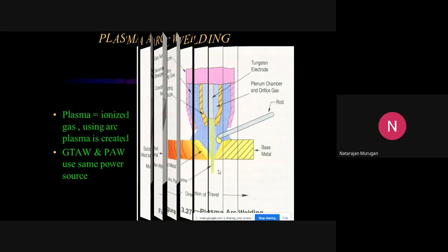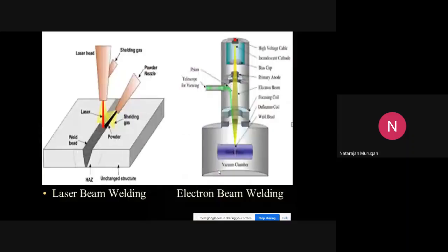So laser beam and electron beam welding are high energy beam welding. The energy level is 10 power 10 watt per meter square, and here you can go up to 10 power 12 energy in electron beam welding. So multi-pass welding is not required. In a single pass, you can weld a 50 mm thick plate without filler.